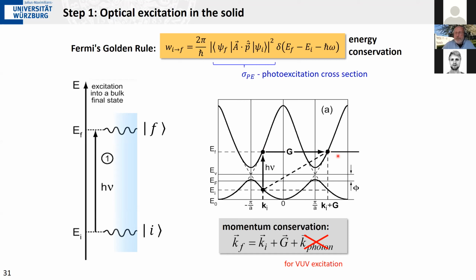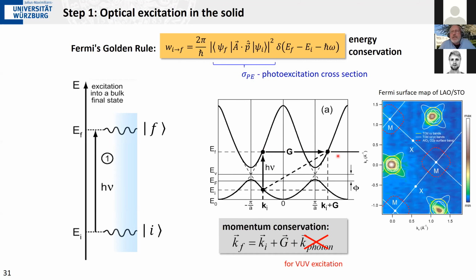And I show you as an example the Fermi surface that can be mapped out for the two-dimensional electron system at the interface of LAO-STO, measured here at different Brillouin zones. This is the original Brillouin zone where you have zero momentum. So this is 0 ky and 0 kx. But as you go to higher momenta, you see that the signal repeats itself because of this periodicity in reciprocal space. That's a very nice representation that reciprocal space is reality. It's not just a mathematical concept. You can really see it in an experiment.